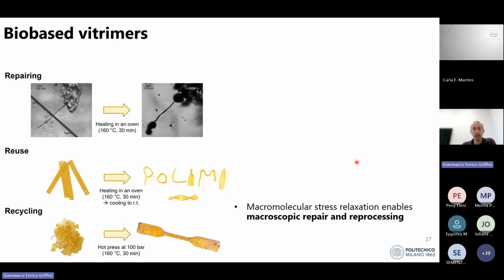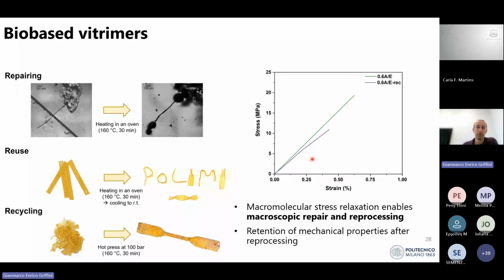Then, in terms of functional response, we evaluated the repairability, reusability, and recyclability of those systems. You see that in all three cases we obtain pretty good results. The material can be easily repaired upon scratch and heating. It can be thermoformed after cross-linking, and it can also be recycled by hot pressing. The recycled material was also tested before and after the recycling process, and you see that we retain most of the mechanical properties, with a little bit of decrease of elongation at break, the ultimate strain.